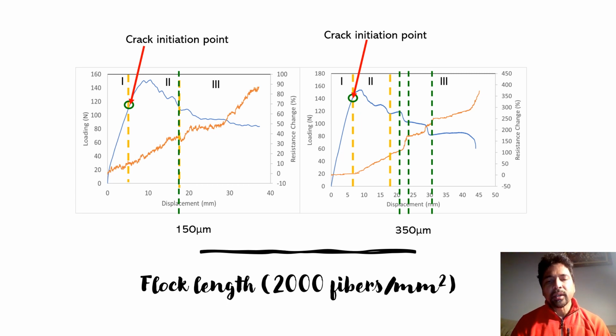So we wanted to achieve crack bridging, and at the same time get a sensitive electrical response from the system. Hence, it seems like the 2000 fibers per millimeter square system with 350 microns carbon fiber length provides both a very high improvement in fracture toughness of 75%, and at the same time provides us a sensitive electrical response as you see in this picture.